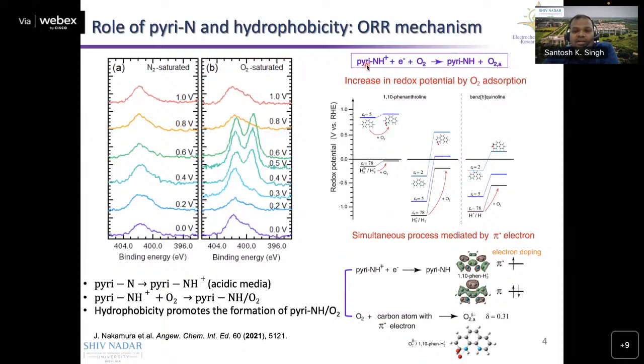So this is the most important reaction in pyridinic nitrogen catalysis, where the pyridinium ion gets an electron and the oxygen adsorbs to the surface, and it converts back to the oxygen adsorbed pyri-NH, which controls the kinetics of this reaction. And this we also proved with DFT calculation by taking different dielectric constants, where dielectric constants of 2 and 5 are hydrophobic. However, dielectric constant 78 corresponds to water, that is a hydrophilic environment. If we see the potential difference between the dielectric constant 78 and the dielectric constant 2 hydrophobic one, the energy barrier is very high in the hydrophilic case.